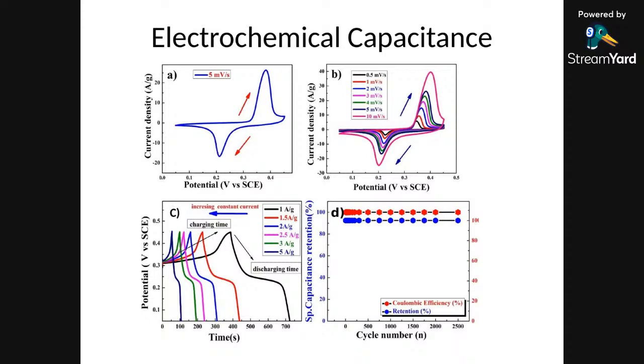It means that when nickel is getting oxidized, the hydroxide ion is actually intercalating through the 3D structure of the hydrated nickel oxalate framework. And even at high current rates, there is not much change in the shape of the peaks, and there is a linear shift with the increasing current rate.